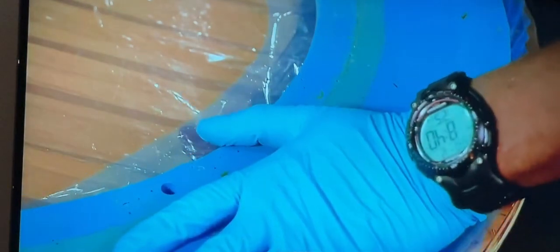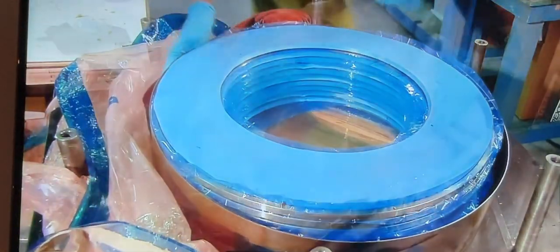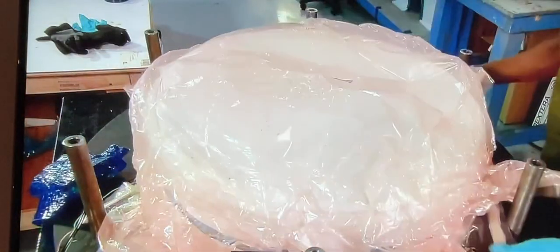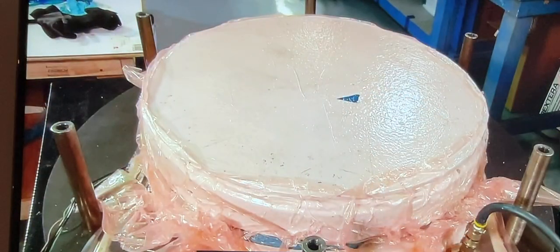He drapes a piece of non-stick plastic film over the mold and adds a silicone pressure pad. He stacks several carbon-filled sidewall molds, each with a silicone pad and plastic film. He wraps a heater pad and a plastic vacuum bag around the stack and activates the vacuum. It sucks out the air to pull the melting carbon fiber to the shape of the molds.